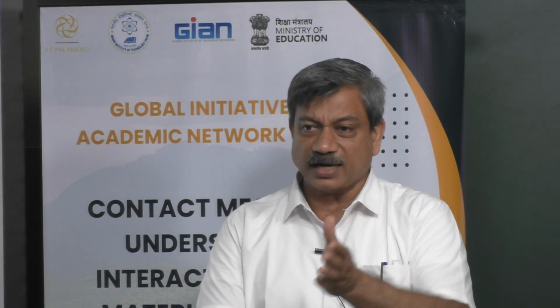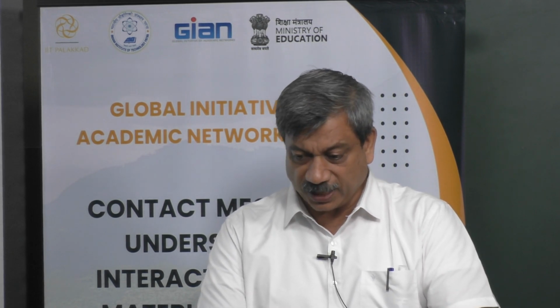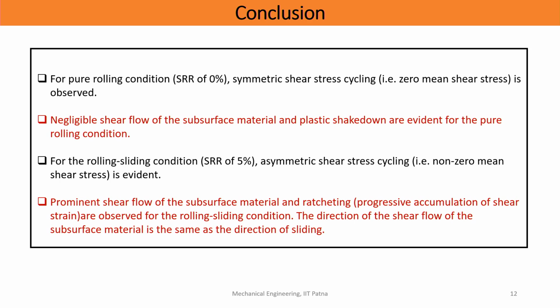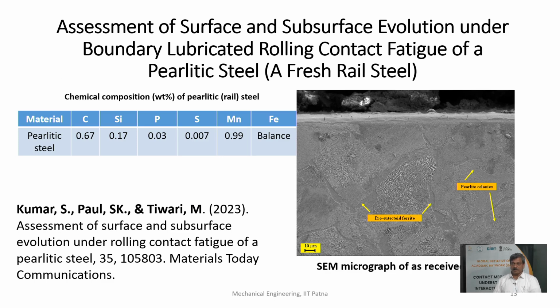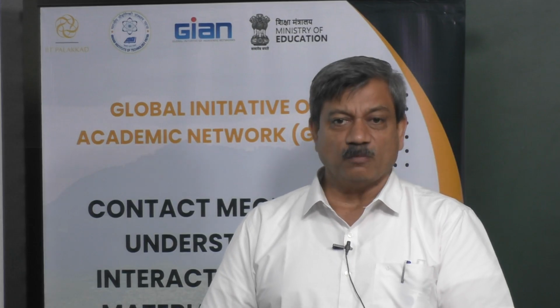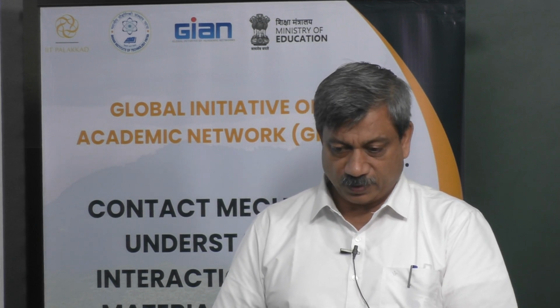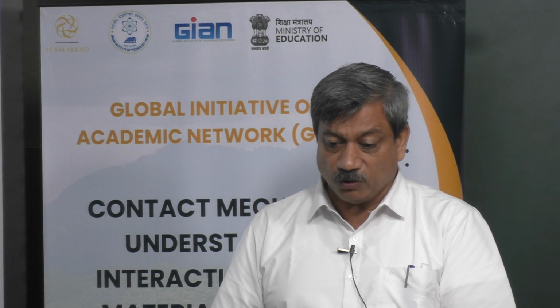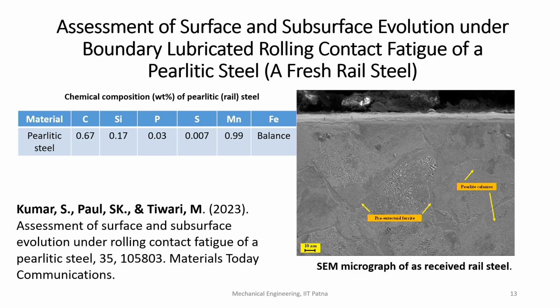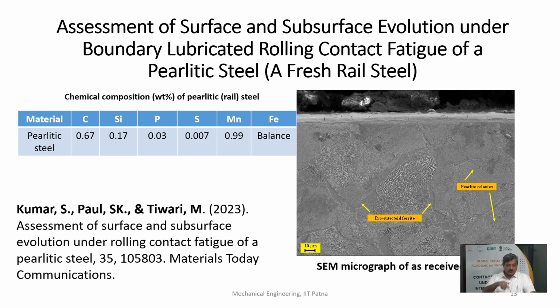Okay. Now there are correlations to this in the experiment. I'll show you in terms of how the cracks have formed, how the failure has happened, but this is what we are getting from this. So this is the important conclusion from this study, which is an Abaqus simulation. Now we start with 2 studies we've done for the same model, but on the experiment on the tribometer. Okay. And this is now boundary lubricated. As I told you, this is 0% and 5% sliding here, 2% SRR in this, and we put as little oil as possible,